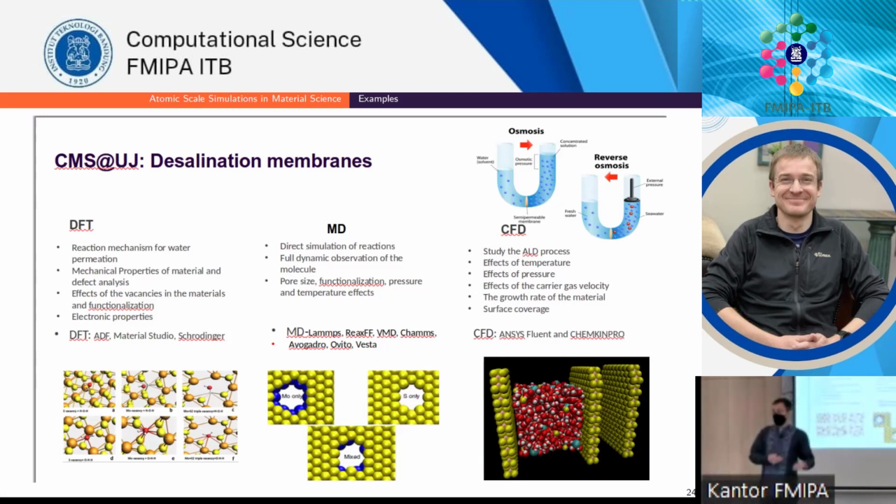Now, in that specific project, DFT was more used as a cross-check, just to make sure that no unexpected effects are happening. So I'm not 100% convinced that this is a perfect simulation. For example, in this model, that's explicit molecular dynamics, using the ReaxFF potential, and I think the water itself was modeled just with a simple interaction potential, so it's not reactive, and there's not a good interaction between the molybdenum surface and the ions, right?